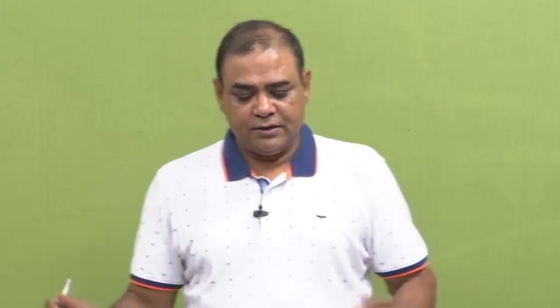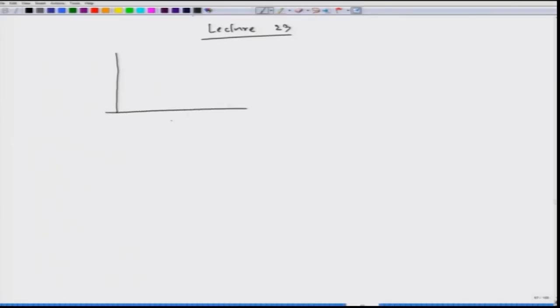In the last lecture we started discussing the nickel-H2O system, and we could draw a Pourbaix diagram involving nickel, Ni++ and NiO. The diagram looks like this: this is the pH axis, this is E in volt. This region was nickel, this was Ni++, and this was NiO. If we extend this line, the point would be 0.11 volt, this is minus 0.250 volt, and this pH was 6.09.